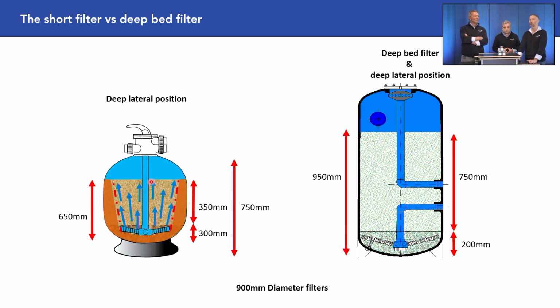But not only that, with such a short filter, you've always got to make space for bed expansion. Like we said earlier on, you need 20% bed expansion. So in many cases that means you can only get a maximum of 350mm, and I have many filters out there with less than that, of filtration media, which would be the grade 1. So our recommendation, with exactly the same diameter filters, so your surface area is the same, is that to facilitate very good filtration, both surface filtration and deep bed filtration, where we're really utilizing the sedimentation phases throughout the deep bed filter, you should go for a higher filter. So it's a deep bed filter with the lateral position as deep down as possible, and like Yasura says, that allows for maximizing the filtration media.